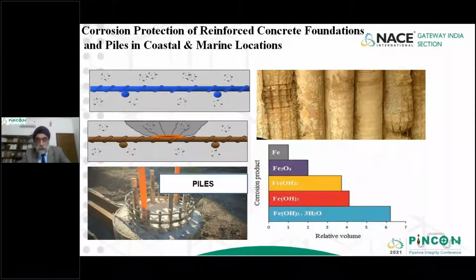The photograph on the right shows you concrete structures where varying degrees of corrosion have occurred on the rebars, and in one of the concrete structures, the entire concrete cover has fallen, causing rapid corrosion of the steel rebar. So once the steel rebar snaps, the structural integrity of the concrete pile will be compromised and it can lead to a collapse of the pile.